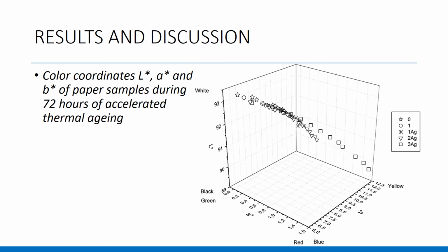Therefore, colloidal silver on the paper surface accelerates the aging and catalyzes the oxidation and hydrolysis of cellulose fibers. This is also confirmed by the observed decrease in the strength indicators, evidencing the destruction of hydrogen bonds between the cellulose fibers in the paper.